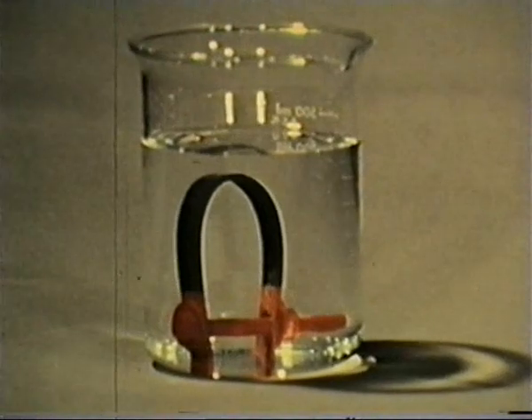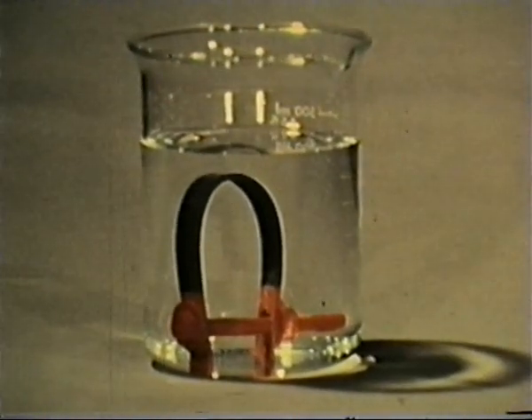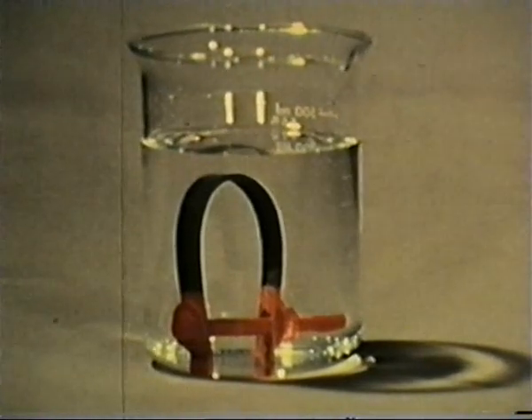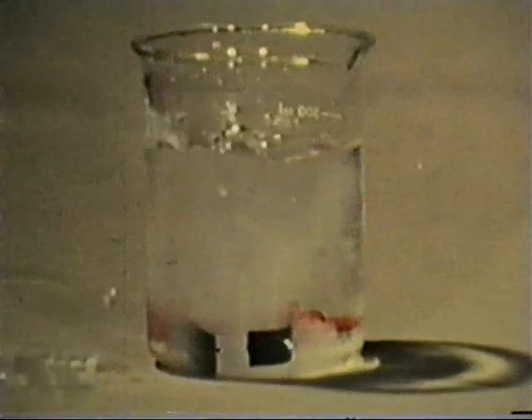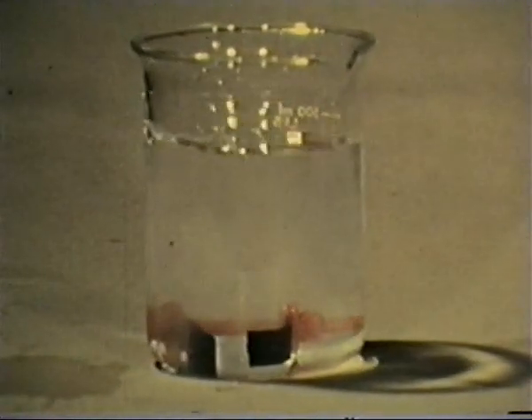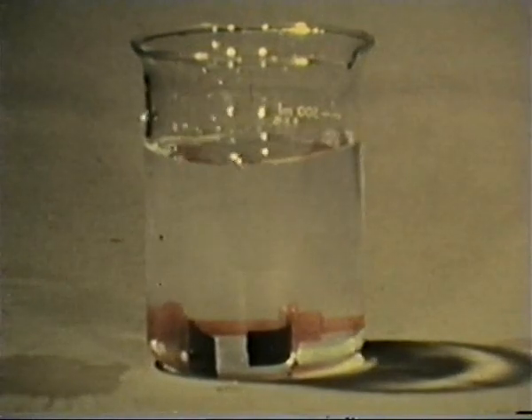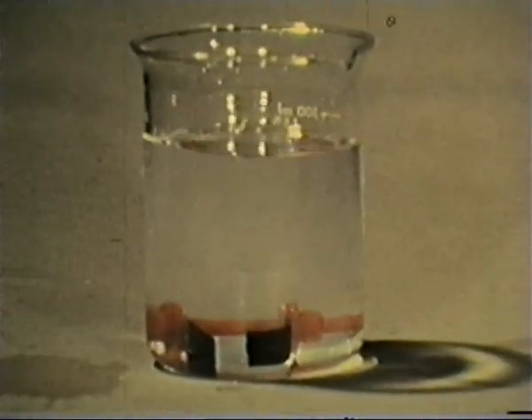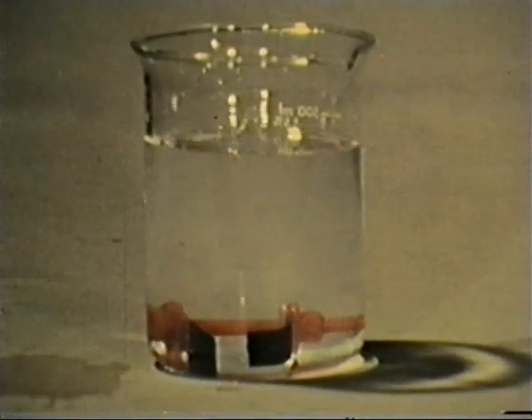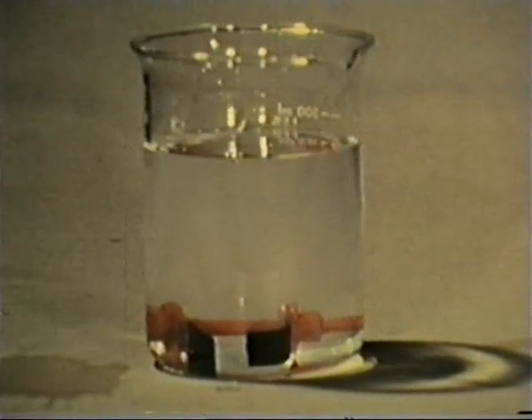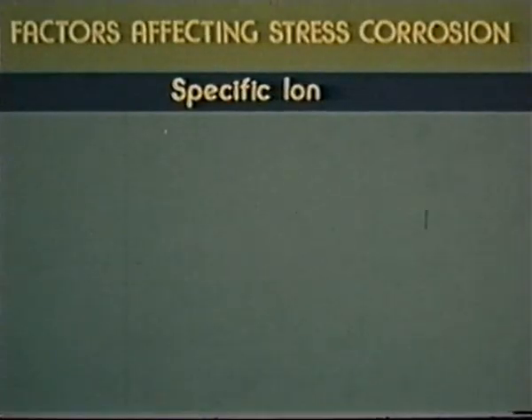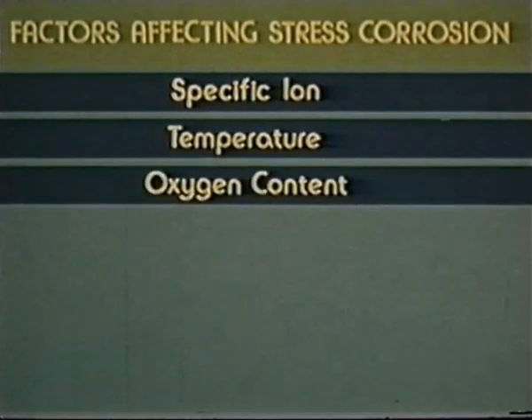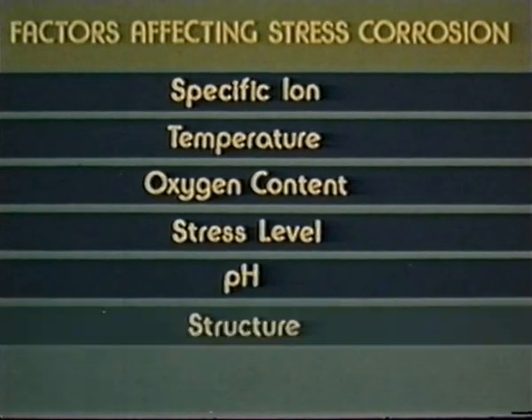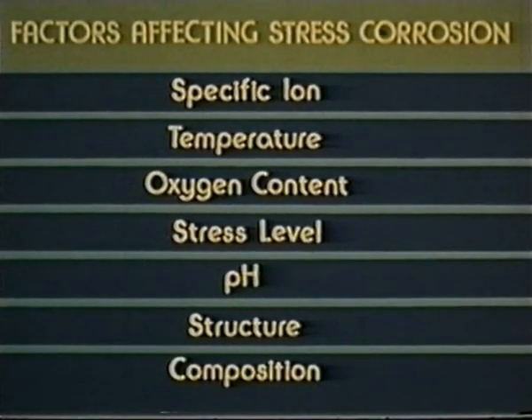Alloy steels with yield strengths greater than about 175,000 pounds per square inch require only the presence of water and a tensile stress to fail through a type of stress corrosion cracking known as hydrogen embrittlement. If hydrogen sulfide is introduced into the aqueous environment, the maximum allowable strength level of such steels must be halved before danger of stress corrosion cracking no longer exists. A complete listing would include practically every alloy system. In addition to the specific ion requirement, other environmental factors affect the susceptibility of metals to stress corrosion cracking. Variations in temperature, oxygen content, stress level, pH, and metal structure and composition are all interrelated in determining overall sensitivity.